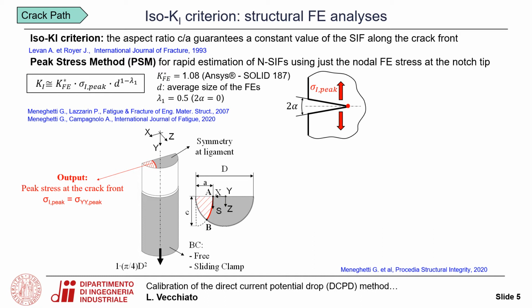In the reported expression, K_FE* is a calibrated constant, d is the average size of the finite elements, and lambda is the stress singularity degree. The crack path and the structural analysis have been performed adopting two different boundary conditions, one of which, sliding clamp, would simulate the effect of rigid machine clamps.